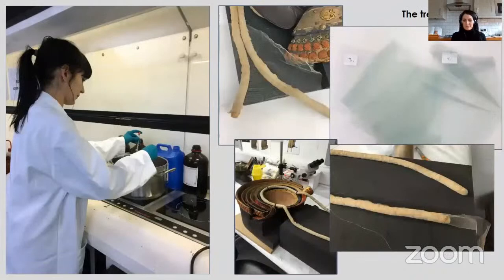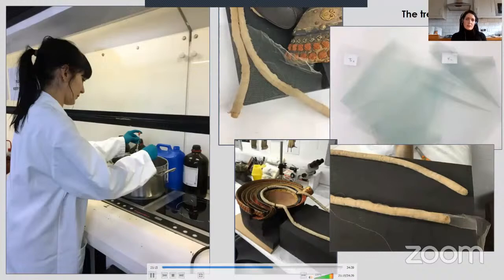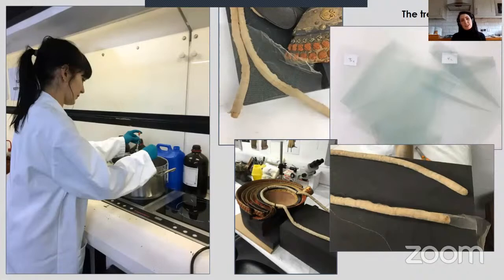Definitely the most time-consuming work in this conservation treatment was the dyeing and application of support fabrics for vulnerable textiles. For the chirimen silk, I dyed conservation-grade nylon net with conservation-safe specialist dyes, which are designed to be colour-fast. And this dyed net was then used to encase the damaged components. For the armour, I had to achieve two good colour matches, so an off-white buff shade for the helmet cords and then a pale blue-green for the thigh guard ties and the shin guard ties.